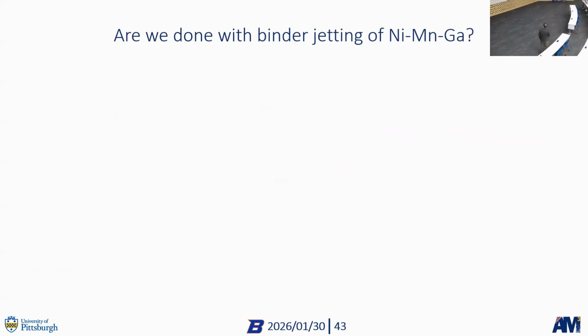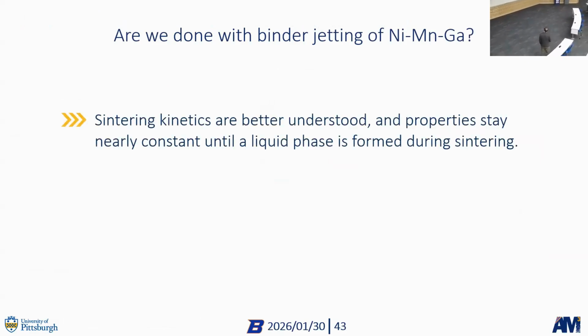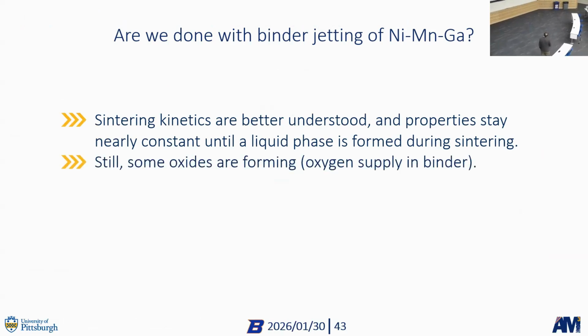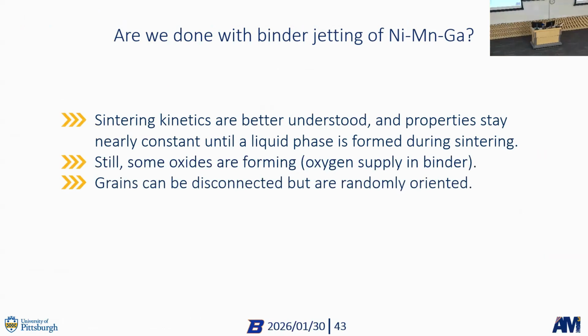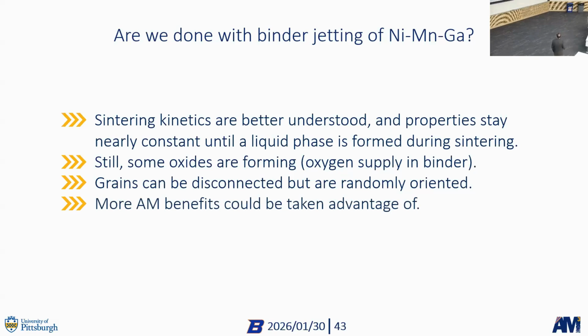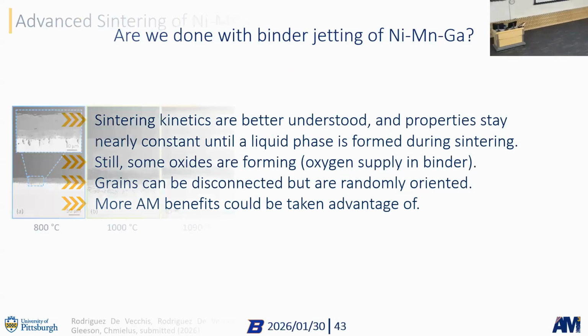So are we done with binder jetting? We understand the sintering kinetics a little bit better, but we still have oxides. You couldn't really see it, but even in argon backfilled sintering, we still have oxide layers, and they're detrimental to functionality. Also, the grains are disconnected, but they are still randomly oriented. We want to get as close to a single crystal as possible, if we can, because that would increase functionality. If you remember, magnetic shape memory alloys function best as single crystals. And we haven't really taken advantage of additive manufacturing too much here. We could just compact these materials as well.